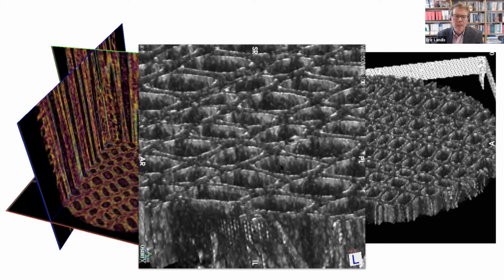And the reason why this is important is that while wood has elastic properties, and for example, wood has a Poisson effect, the Poisson effect is not like one you would see in a homogeneous continuum, because the Poisson effect is dictated not by the elastic properties of the continuum, but in fact by the structure. The cellular structure, and how the cells are arranged, is going to dictate the elastic constants.